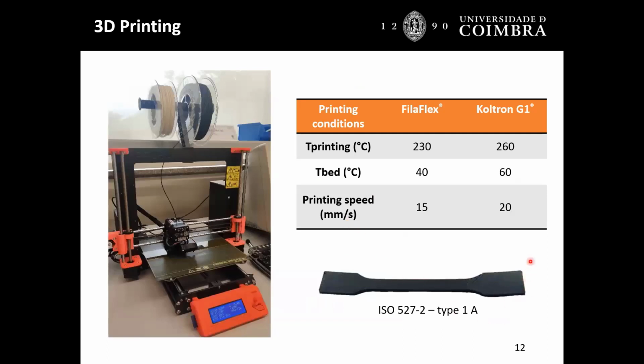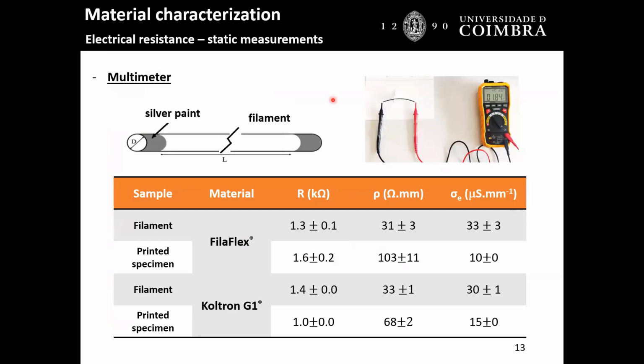We made tensile test filaments according to the ISO standard, and we printed them at 230 to 260, bed temperature 40 and 60, and a very slow printing speed, because it was not easy to print, mostly the PVDF-based polymer. Okay. Now for the electric measurements, we tried several things.